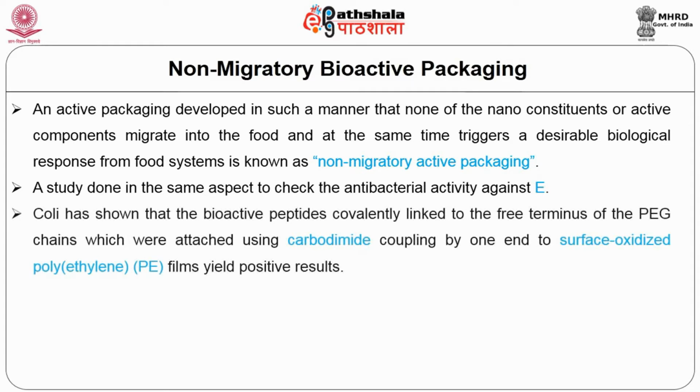A study done in the same aspect to check the antibacterial activity against Escherichia coli has shown that bioactive peptides covalently linked to the free terminus of polyethylene glycol chains, which are attached using carbodiimide coupling by one end to surface oxidized polyethylene films, yield positive results.